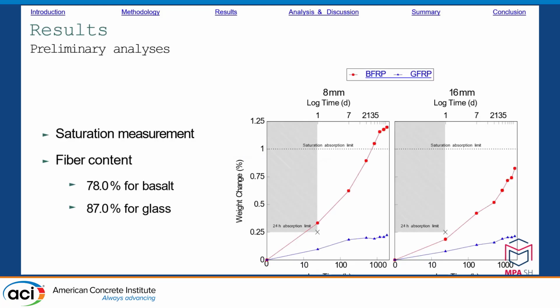While the test bars, which were to be exposed to frost, were in the water bath, a saturation measurement was carried out in parallel. The results of the saturation measurement can be seen in the graph. All samples increased in weight during this period, but the basalt fiber rods significantly more than the glass fiber rods. The basalt fiber rods with a diameter of 8 mm did not meet the criteria of the saturation maximum and the 24 hours absorption limit.